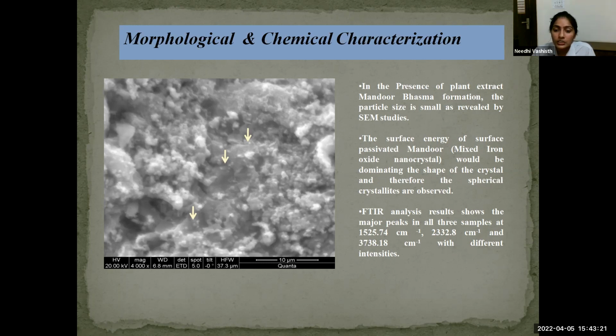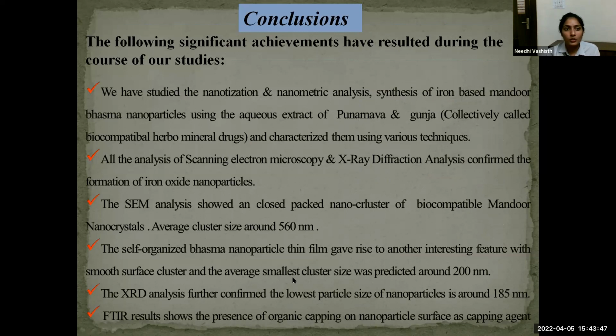The FTIR, that is Fourier transform infrared, analysis result shows major peaks in all 3 samples at 1525.74 per centimeter, 2332.8 per centimeter, and 3738.18 per centimeter, with different intensities. The next one is our conclusion.